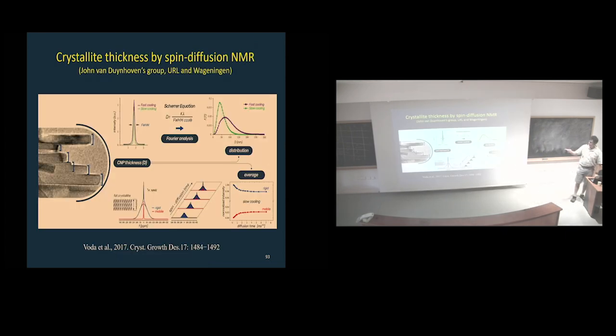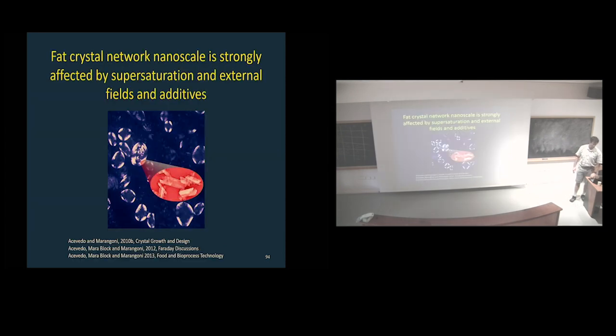John van Duynhoven from Unilever has taken this further, and he now uses spin diffusion NMR. And he manages to get also domain sizes from that, and he's doing funky things like, if you have a wider distribution of domain sizes, you have a more plastic material. It gets really interesting, more plasticity related to your heterogeneity in the distribution of nanoplatelet sizes and thicknesses.